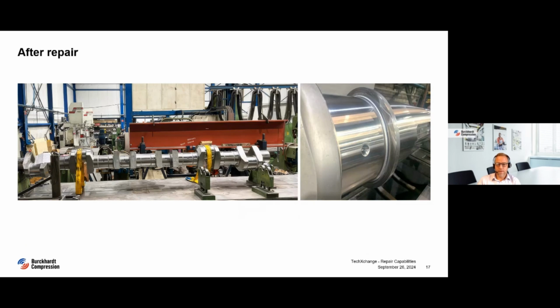Here you can see a completely repaired crankshaft with the 13 bearing surfaces, which are laser cladded with Stellite 21. All surfaces are ground and also the lubrication oil holes are cleaned, and the oil radius was polished by hand.